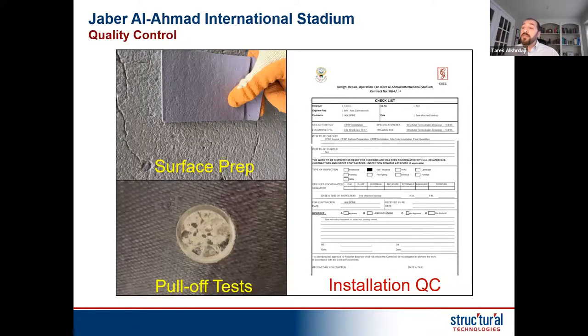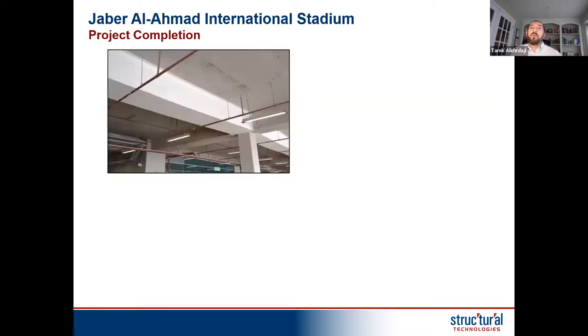An important thing during surface prep is quality control, where you verify the surface, but also a bond test is done to verify the bond strength of the FRP to the concrete substrate. Typical QC requires recording the temperature, which lot number was used, where it was installed, the pull tension, and the pull strength. There's a minimum of 1.4 MPa required as bond by the Canadian standards, to ensure that the FRP is fully bonded. So that is the minimum. And typically, most of the time, if the concrete is good, you can easily achieve 3 or sometimes even more than 3 MPa in bond strength.